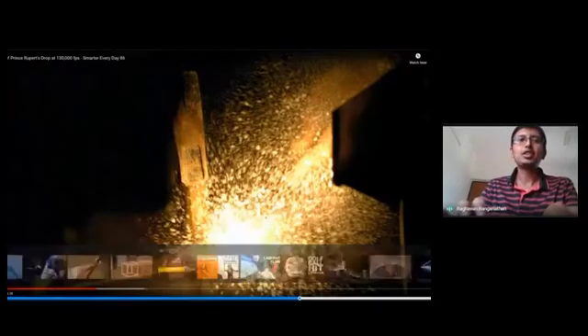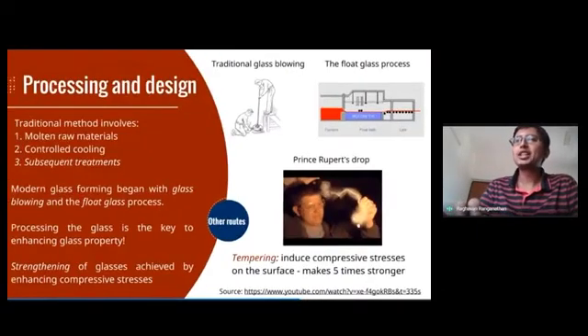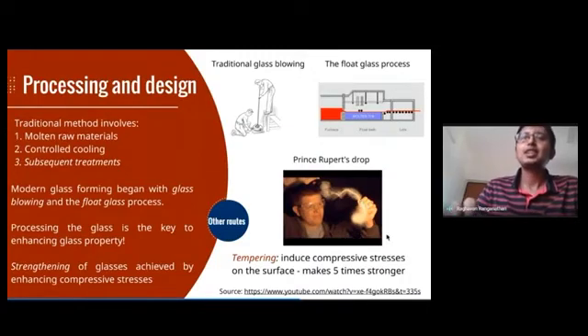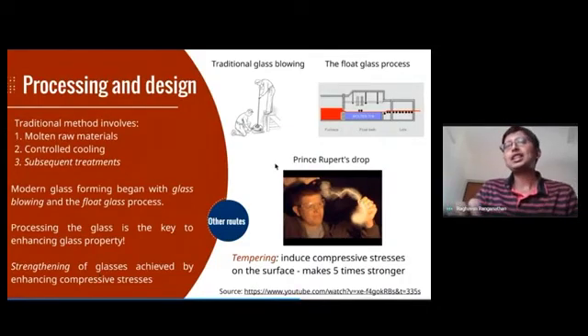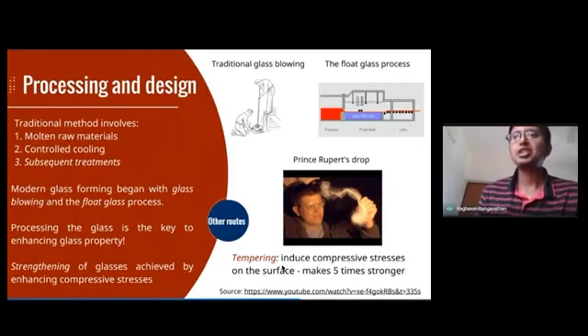Okay, what you saw there was a glass structure that had a lot of compressive stress at the head. Okay, and this is a very thin tail that the glass structure has, and this tail is essentially under a lot of tensile stress. And it turns out that tensile stresses are very bad for strength of the glass. And when the hammer actually impinges on the head, it does not break from the head. In fact, what happens is the stresses get transferred through the tail, and the tail eventually breaks first, and then the glass subsequently shatters. So this is a very important property that can be obtained by sufficient thermal processing.